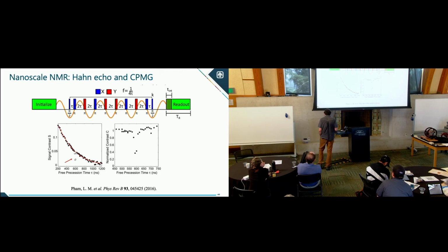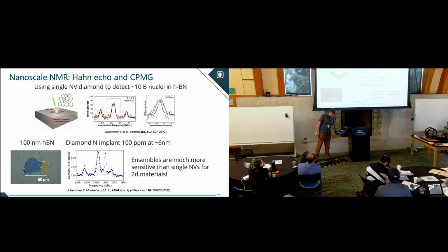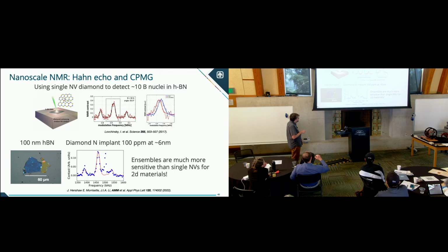Now that's for nitrogen, which is already there. What if you want to look at something else? So in this case, we actually used hBN, which has boron in it, and we wanted to try nanoscale nuclear magnetic resonance. By doing this dynamic decoupling sequence and tuning our tau, we can lock into different frequencies. And what we have here is actually the spectrum, the nuclear magnetic resonance spectrum of a few layers of hexagonal boron nitride. So now we're actually doing magnetic spectroscopy at the nanoscale.